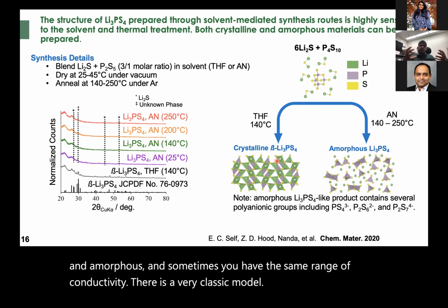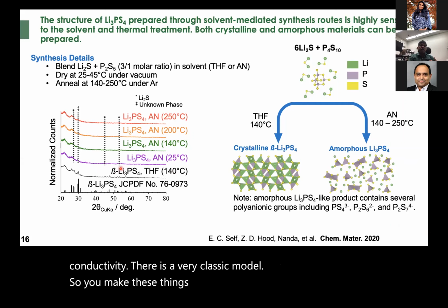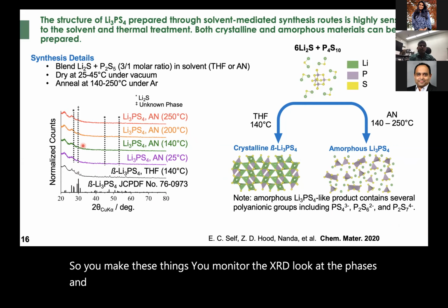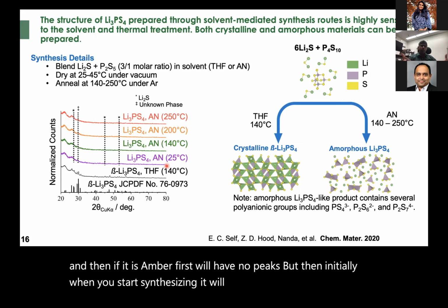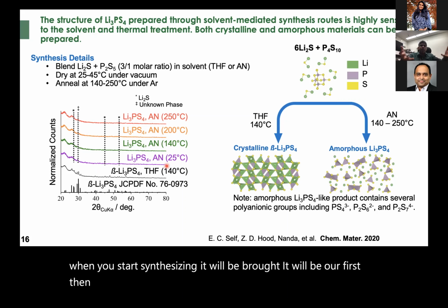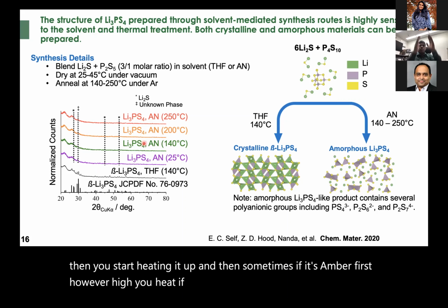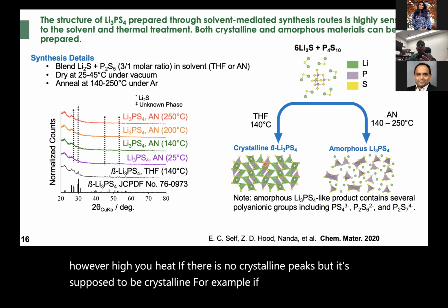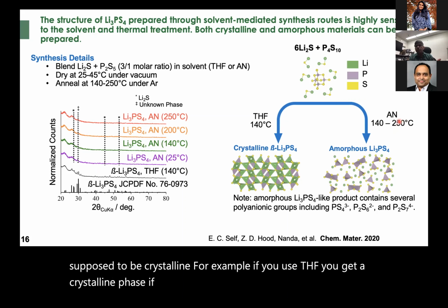So you make these things, you monitor the XRD, look at the phases. If it is amorphous, it will have no peaks. When you initially start synthesizing it, it will be broad, it will be amorphous. Then you start heating it up. Sometimes if it is amorphous, however high you heat, there are no crystalline peaks, but it's supposed to be crystalline. For example, if you use THF, you get a crystalline phase. If you use acetonitrile, you always get amorphous.